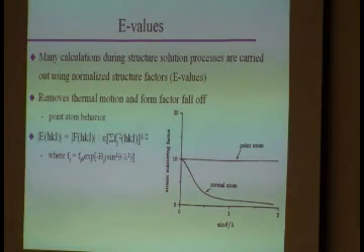Okay? And what the normalization does is it removes the drop-off of your F's, of your small f's, your atomic scattering factors as a function of angle. As you might recall, especially from the one homework set, you have this drop-off in F as a function of sine theta over lambda. And it also removes the thermal motion.